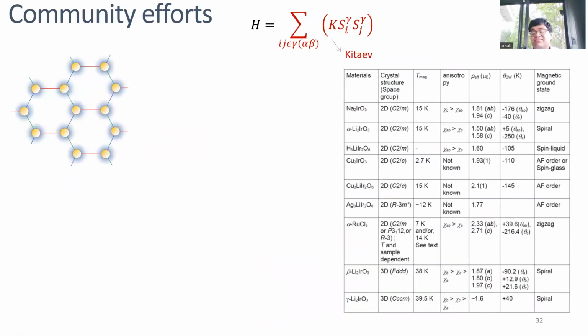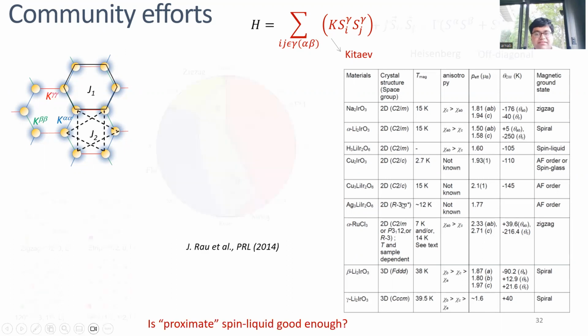There are several material candidates which have been proposed for realizing this state. One material on which I have worked quite a bit is alpha ruthenium trichloride, which was basically discovered by us independently from the Toronto group. And we did some of the first measurements on the samples, some of which I will be talking about. There are many other candidates with varying degrees of success. In fact, there is a new candidate, barium cobalt arsenate, which we have also created in our labs, which was first proposed by Peter Armitage and Bob Cava, who made the first crystals. But we also have them in our lab where we are doing measurements on them. I will not be talking about that in this talk.